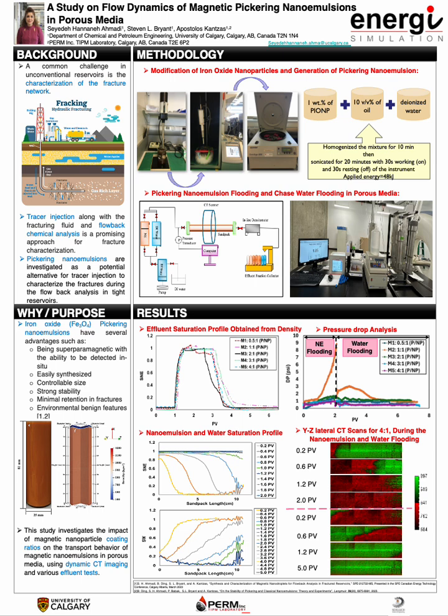And then we mix 1 weight percent of polymer-coated iron oxide nanoparticle, 10 volume percent of oil, where the oil that we used was dodecane, and deionized water, mixing them with a homogenizer, and after that applying energy with a sonicator to disperse oil in the system and make a nanoemulsion.